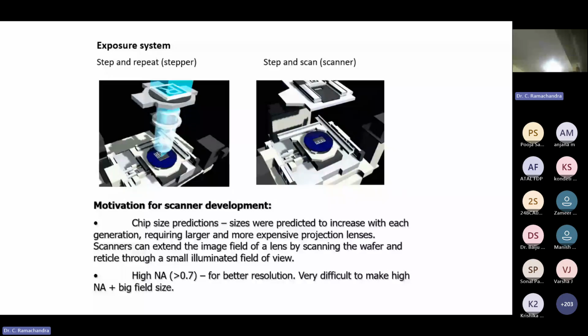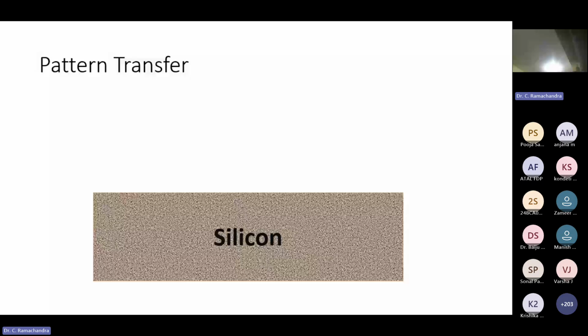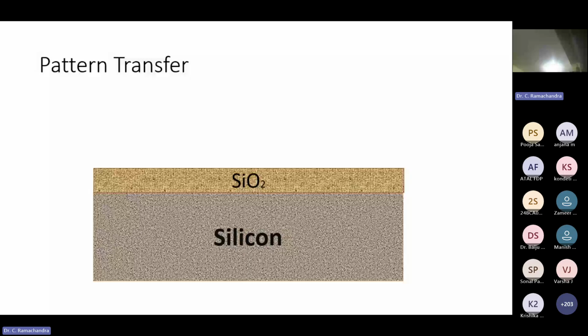Now, how do we transfer the pattern from mask to the silicon? As I said, it is not a single step process. It has multiple steps. This is the starting material silicon. I cannot transfer the pattern directly from photoresist to the silicon. The first step is I deposit silicon dioxide. So on the silicon, I deposit a thin layer of silicon dioxide. This dioxide, I'm going to remove it later on. That means it does not have any performance in the device. Therefore, it does not need to be very good quality. So generally we use wet oxide for growing this one, which is very fast and low cost.